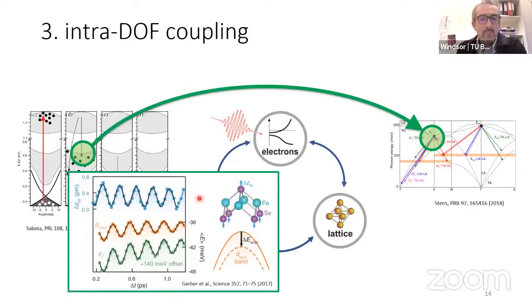Here we have a paper about iron selenium that was published a few years ago, where there are two key observations. One is that, using X-ray diffraction, they observed this motion of these atoms. These are selenium atoms moving up and down in a coherent fashion. This is shown here, and the y-axis here is this delta Z, which is in units of length.